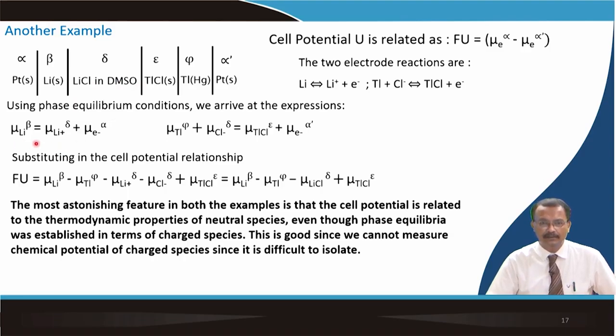So, you can write the expression for chemical potential for the lithium as well as for thallium chloride, and then substitute this value the way I did it in the last case, and you can basically estimate the VOC, voltage under open circuit condition. And you can see this is a nice example that shows the cell potential is related to the thermodynamic properties of the neutral species, because the charged species somehow get cancelled.